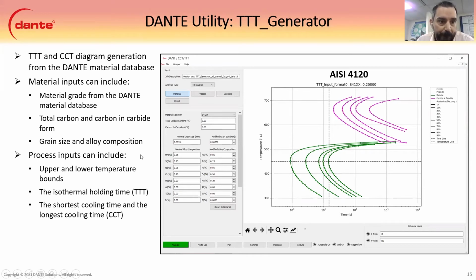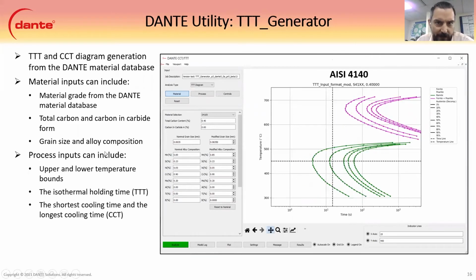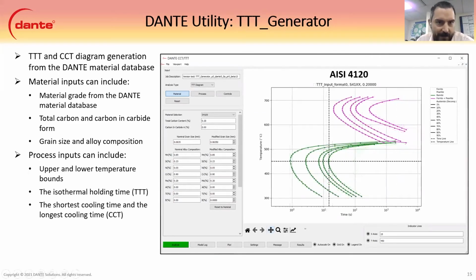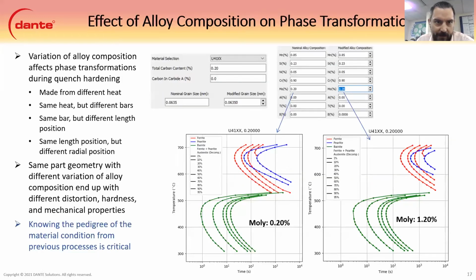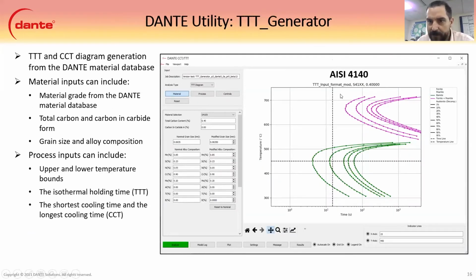So the process inputs include upper and lower temperature bounds. Same way though, they choose the upper and lower temperature bounds. So it's basically how tall to make the graph and how low. So this one would be 750 to 300. TTTs don't have martensite transformation, so otherwise we don't have that line there. And the isothermal hold time, so how long to span the x-axis for you, and the shortest cooling time, so how short, 1 second here, 10 seconds there.